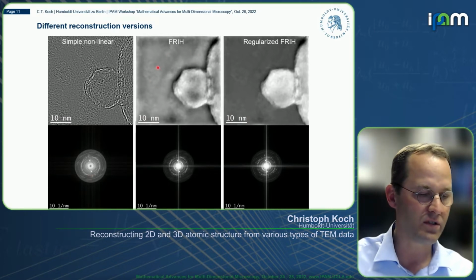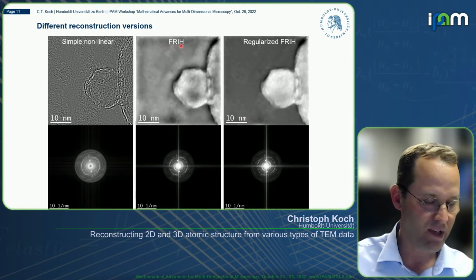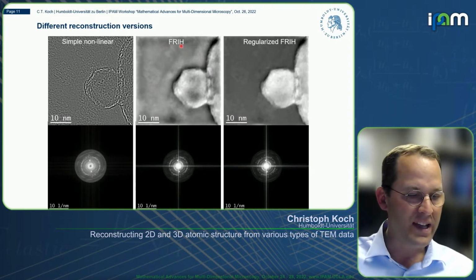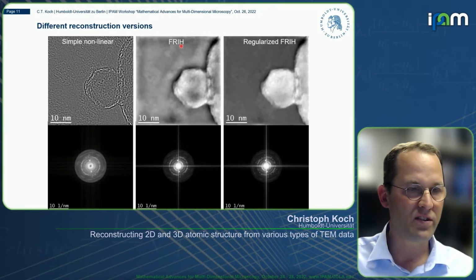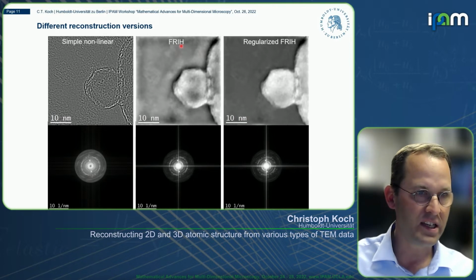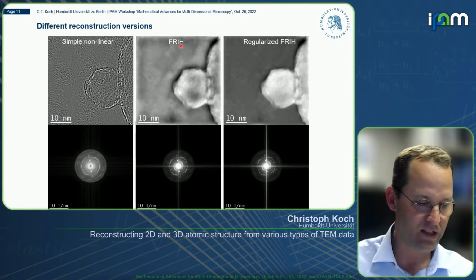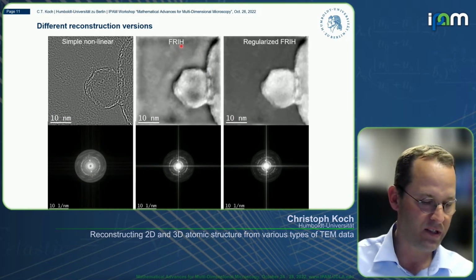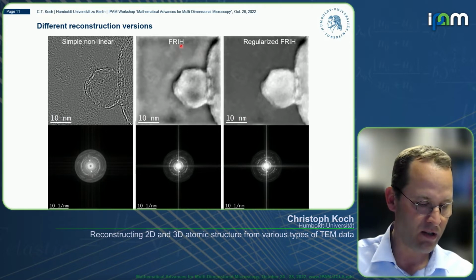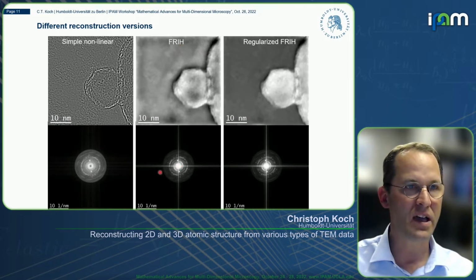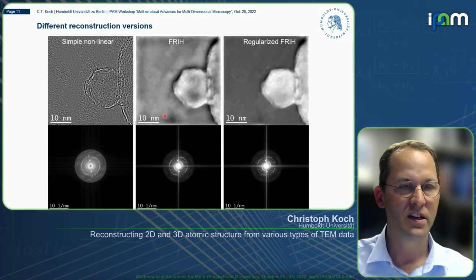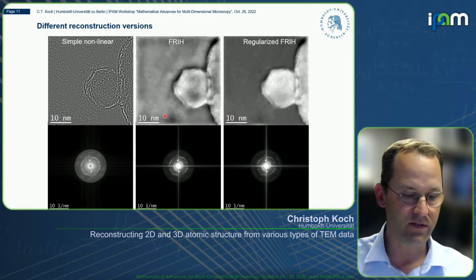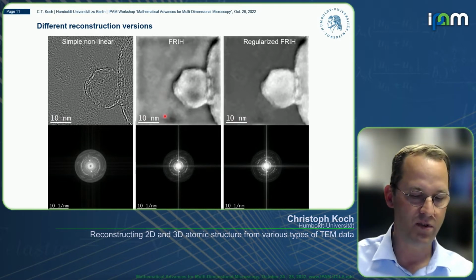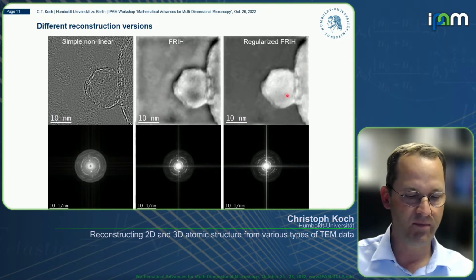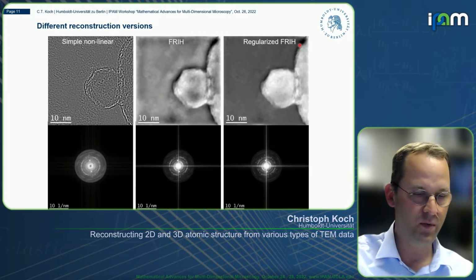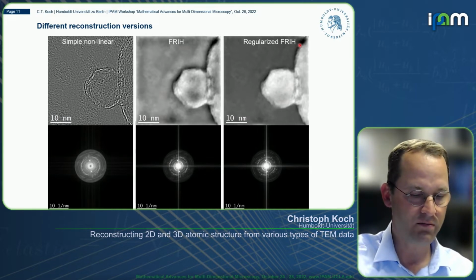This is already different here. This stands for full resolution inline holography. It combines different algorithms together and uses the strength of, for example, the transport of intensity equation to extrapolate to low spatial frequencies. And now you can see this black hole is gone, and a lot of the low spatial frequencies have come back. But there's this problem with the transport of intensity equation that it also enhances noise at low spatial frequencies, and applying this regularization gives a more reasonable reconstruction. There may still be some artifacts here and there, but at least the reconstruction has improved a lot.